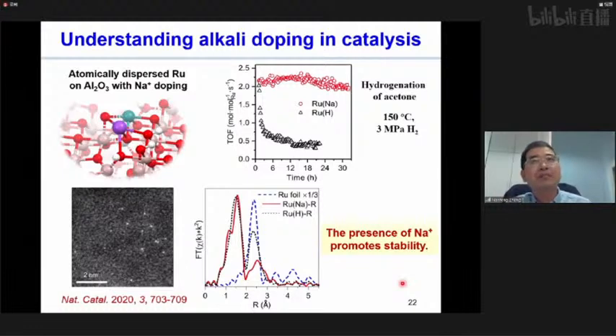Here is another example. Alkaline doping is a really interesting method for us to promote heterogeneous catalysis, and it has been widely demonstrated in the literature. However, why alkaline doping can promote the catalysis is still under debate. So in this example, we prepared atomically dispersed ruthenium with either sodium hydroxide or ammonium as a precipitator. As you can see here, both catalysts have quite similar initial catalytic activity, right?